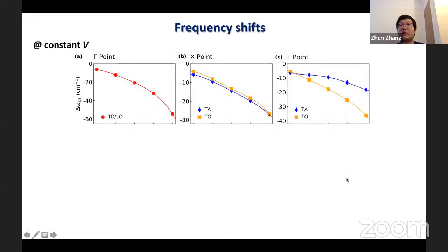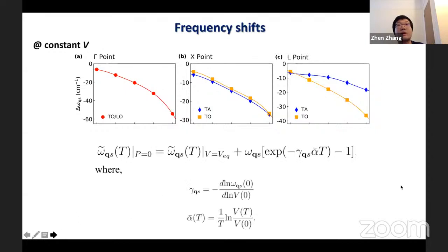Next, I will compare the frequency shifts obtained from phonon quasi-particles to the neutron scattering experiments. Since the MD were simulated in the NVT ensemble, we obtained renormalized frequencies first at constant volume. Here are the obtained renormalized frequencies at 3 Q points in the Brillouin zone for 5 phonon modes. By using the following formulas, frequencies at constant volume can be converted to constant zero pressure condition.